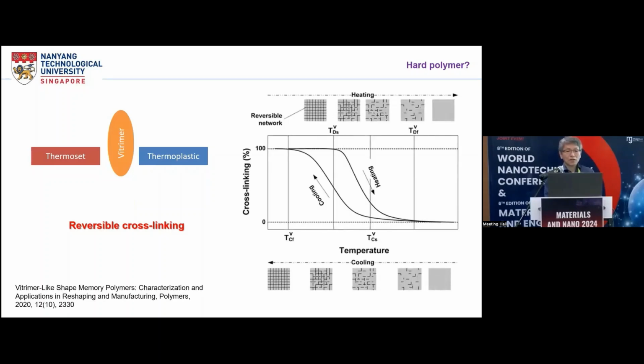And this illustrates the cross-linking against temperature relationship for this material. So at low temperature, it's fully cross-linked, 100%. Upon heating, over here, cross-links start to disappear gradually. So eventually like this at a high temperature, it becomes thermoplastic. But at low temperature it is thermoset. And upon cooling, the cross-linking is going to fully recover and therefore become thermoset again. So this is the feature of vitrimer. And then let's give a little introduction about one particular commercially available vitrimer, that's TPU, thermoplastic polyurethane.